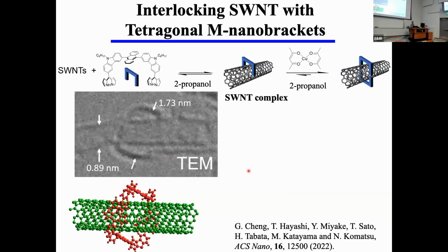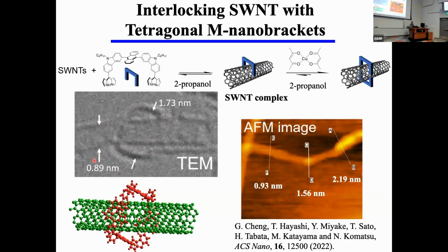So we have a collaborator and a very good specialist of TEM, Hayashi sensei at Shinshu University. And this is an interlocking structure. So this carbon nanotube is interlocked, and the distance is 1.73, and the interlocked carbon nanotube size is 0.89 nanometer. And this is an AFM image, which supports this interlocking structure. So this is the diameter of the pristine carbon nanotube, 0.93 nanometer.